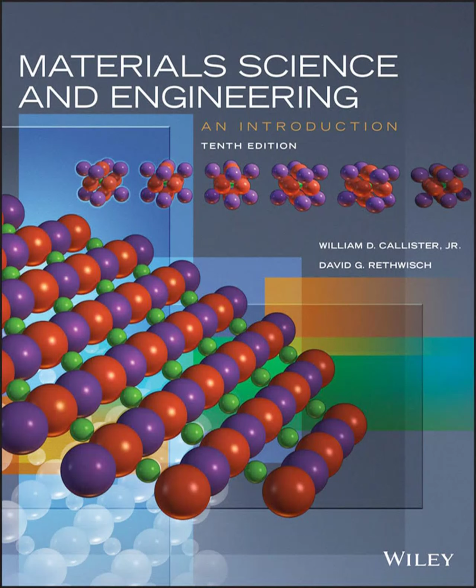So if materials absorb energy through these phonons, I'd think heat capacity just goes up steadily with temperature. But you said it's not quite that simple. It's not quite linear, no. It's a great question. If you plot heat capacity against temperature, you see this distinct curve. At absolute zero, 0 Kelvin, there's basically no vibration, so heat capacity is zero. Then it rises really rapidly with temperature. At very low temperatures, it follows a cubic relationship, C_V equals A times T cubed. Wow, okay. But it doesn't just keep climbing forever. No, it doesn't. That's the interesting part.